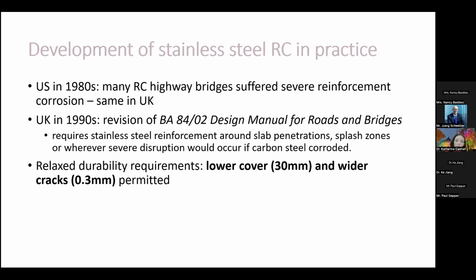Interestingly, it also allowed for some relaxed durability requirements, so lower cover, 30 millimeters rather than 50 millimeters as was standard for the carbon steel, and wider cracks were also permitted. So there was a relaxation in some of the durability requirements. Coming from where we're at now, which I'll go into in a little bit more detail in future slides, I'm uncertain as to where those limits came from or what the background for them was. But nevertheless, I guess it shows the faith in the performance of stainless steel reinforcement and its durability.